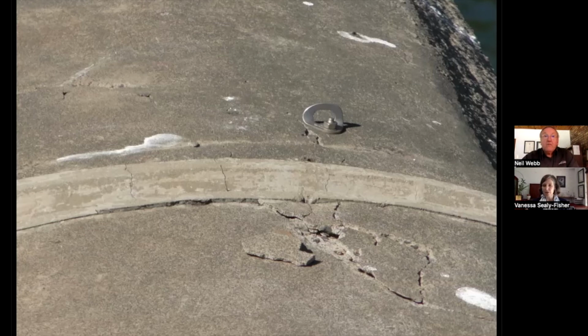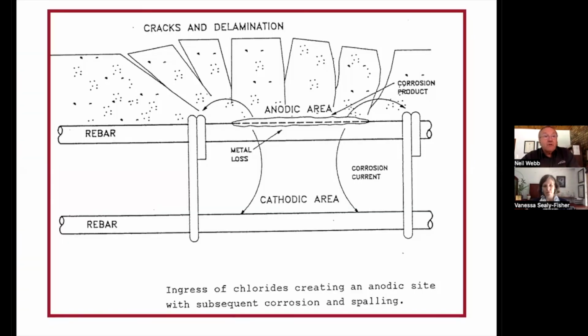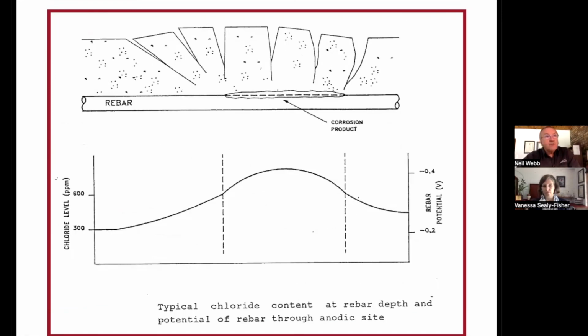Is that an option? For sure. If you consider a typical reinforced concrete structure where the outer layer of reinforcing is corroding, as you can see here, before this actually happens, the pH of the concrete around the steel will have changed, the potential will have changed. And if we were to plot the potential of the reinforcing and also look at perhaps the chloride levels, you will see that there is a significant increase in chloride content in the area that has got the problem. May have been a pre-existing crack, it may have just been a piece of porous concrete, may have been an area of low cover, anything like that. And you get a corresponding change in potential.